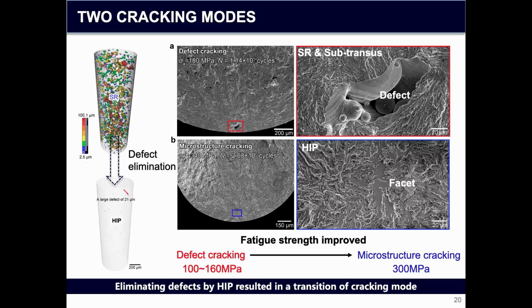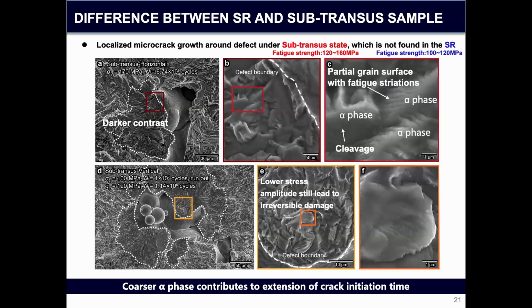has transited to microstructure cracking because there are no defects at all after HIP, and the fatigue strength has been raised by about 2 times. So this is the HIP's function, and we also find there are differences between SR and sub-transus samples. The essential thing is that we found localized micro crack growth from defects under sub-transus states, which is not in the SR states. And this kind of micro crack growth actually extends the crack initiation time for the sub-transus states, which also leads to the higher fatigue strength.